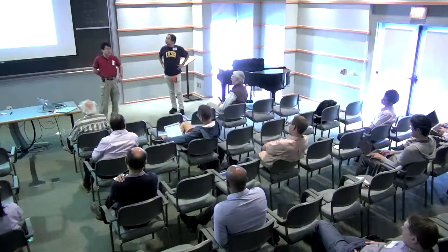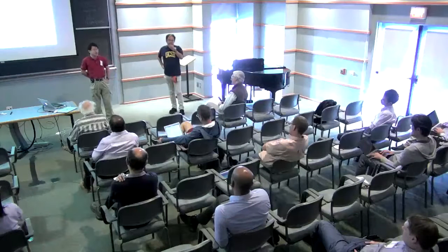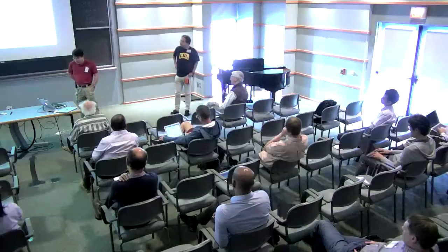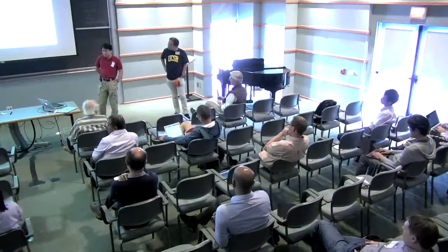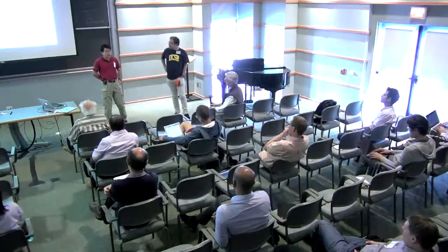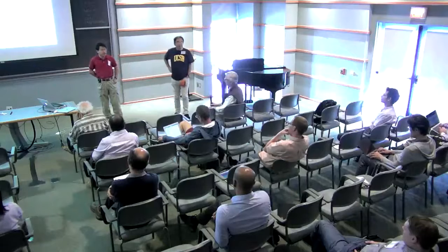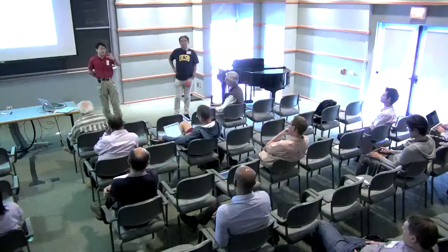I think the Ising degree of freedom is maybe not as severe as for this Kramers doublet, which appears for this ytterbium compound. But the disorder doesn't play any role in generating the intrinsic transverse field, right? Or does it? That's a very good question, actually. If you want to include the effect of disorder, first of all, we have this transverse field that models the splitting between these two singlets.